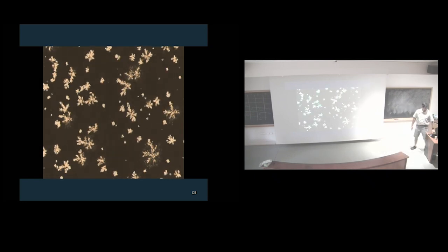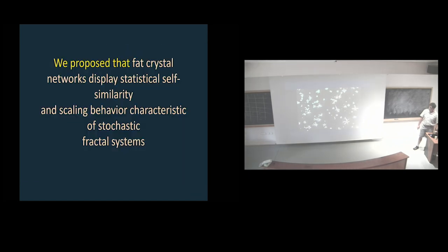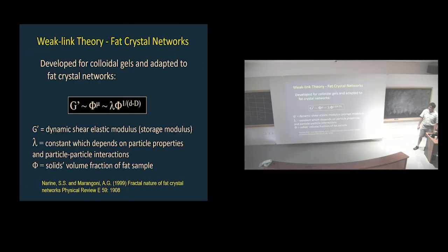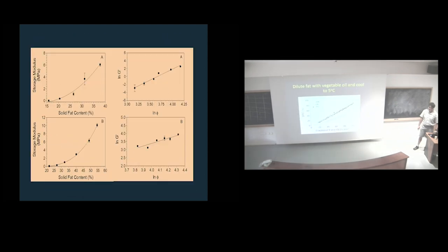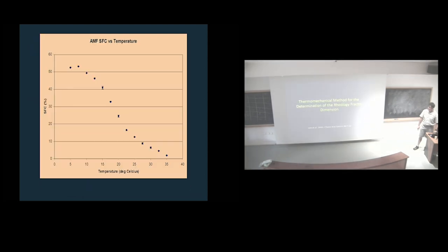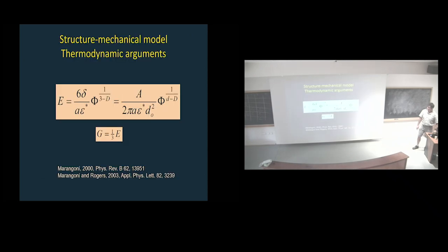And then we can look at the growth of the crystal and the formation of these clusters in time. And we eventually did that. I'm just going to get to the point, the final formula. We managed to develop the formalism not only to describe, according to the weak link regime, the exponent of the volume fraction term, that's the amount of solids, like 10% SFC. And here we also derive the pre-exponential term. The way I simplify the van der Waals things to the point where I use a semi-classical approach, that's your interfacial tension. And that's the size of a platelet, and that's a critical strain when you are pulling things apart and forces are no more.